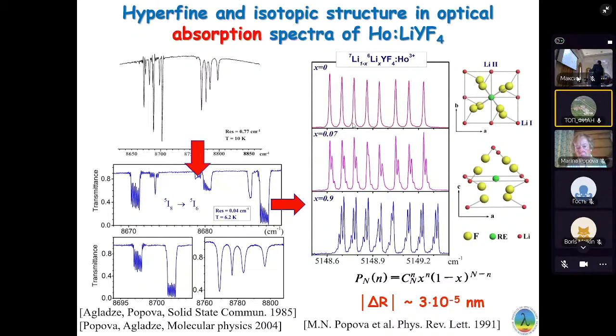As well, by Marina Popova and Nikolai Agladze, an isotopic structure was observed because of the lithium isotope disorder. So there are lithium-7 crystals, lithium-7 with a small concentration of lithium-6, and lithium-6 with a small concentration of lithium-7. So it's a structure in structure.